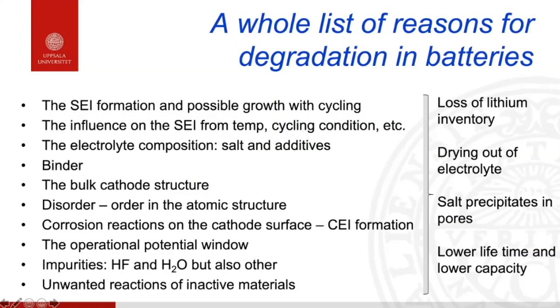And of course, there's a whole list of reasons for degradation in batteries. If you make it very short, you have loss of lithium inventory, you can have drying out of the electrolyte, and you have salt that precipitates in the different pores. If you get lower lifetime, you get, of course, lower capacity, and it has to do with the bulk structure, the interface structure to the different components, what operational window you have, impurities, etc., etc.